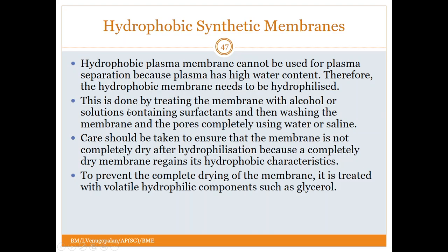So once you wash the membrane thoroughly to remove the alcohol or surfactant, treat it with glycerol, and then that would help the membrane maintain its moisture, and that's how hydrophobic synthetic membranes are converted into hydrophilic membranes, and then used as plasma separator.